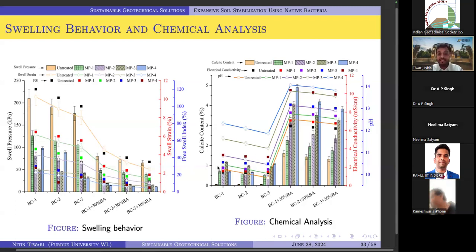And we observe, yes. Initially we had almost 0% of the calcite. In the normal soil, almost 1.2, 1.3% of calcite content is formed. But when it comes to the bottom ash, because bottom ash is also helpful for the cementation effect and everything, we achieve almost 5% of the calcite content, which is really, really huge for the binding and everything. So you'll find a rock kind of soil sample once you do that.